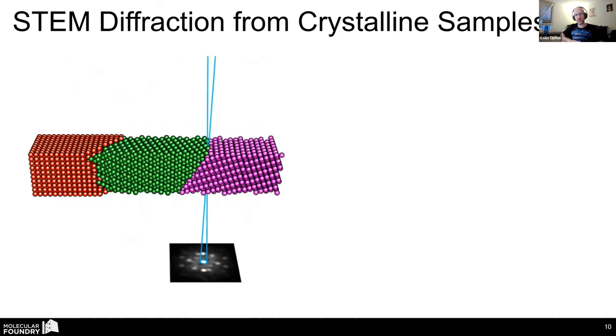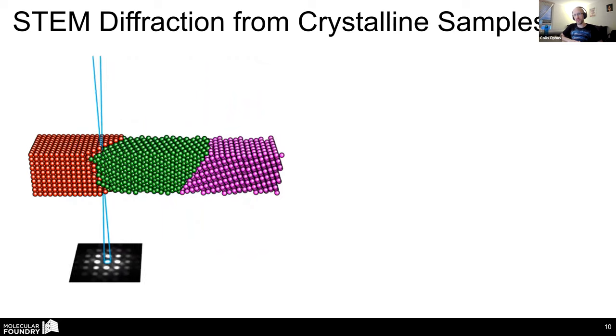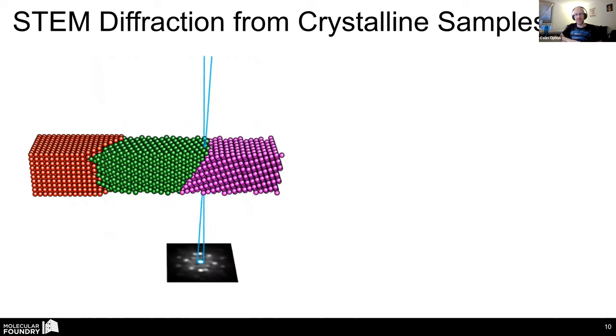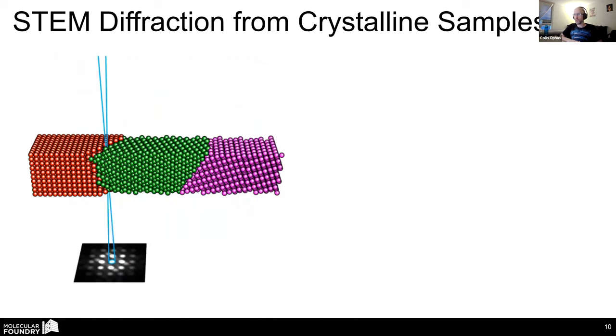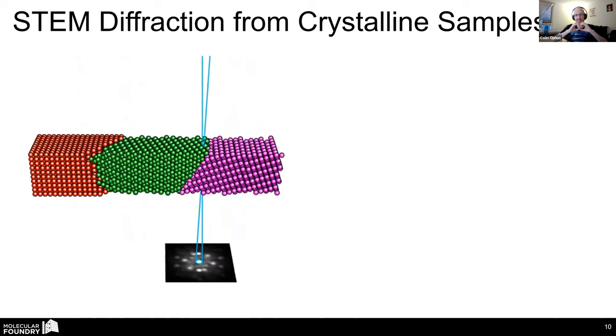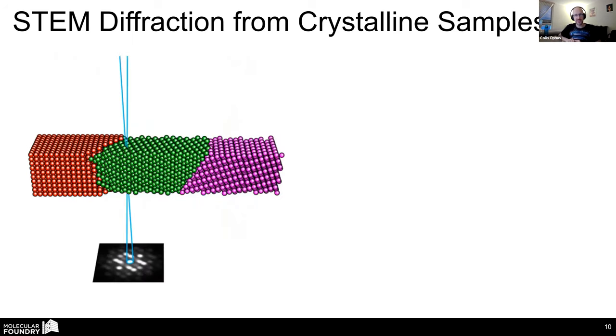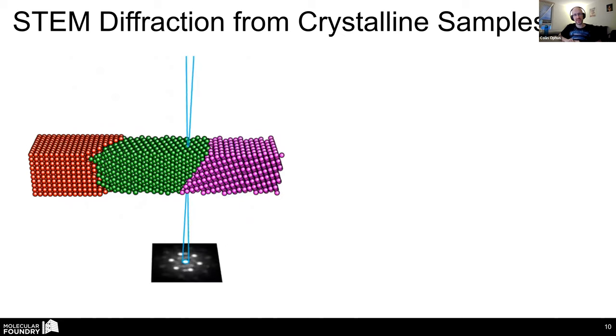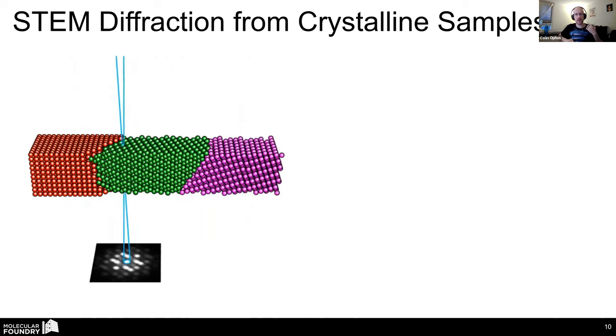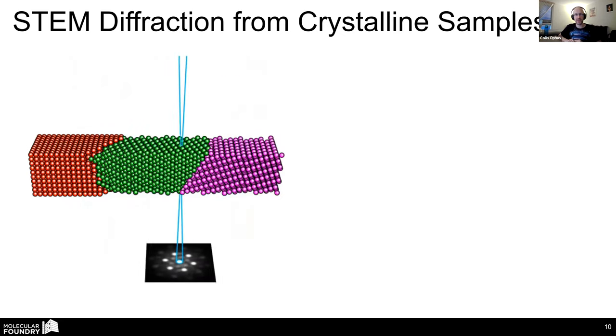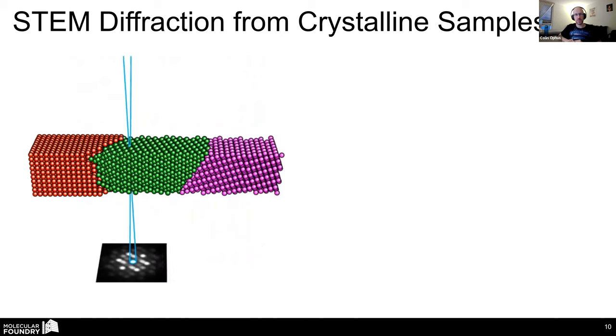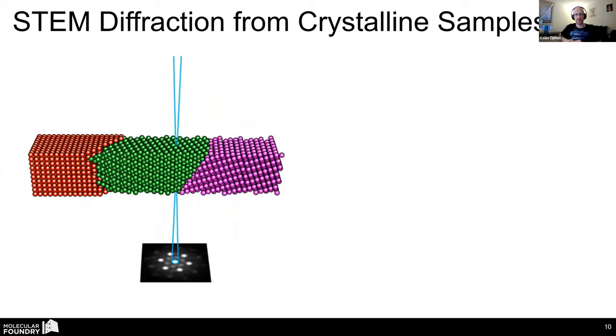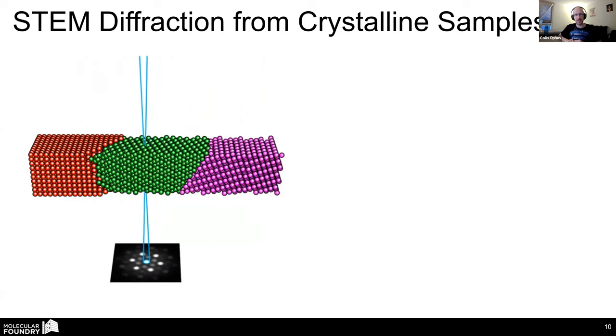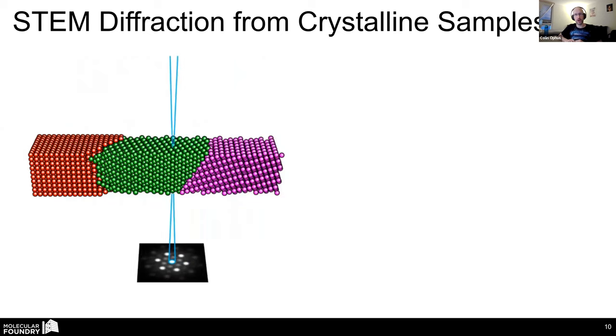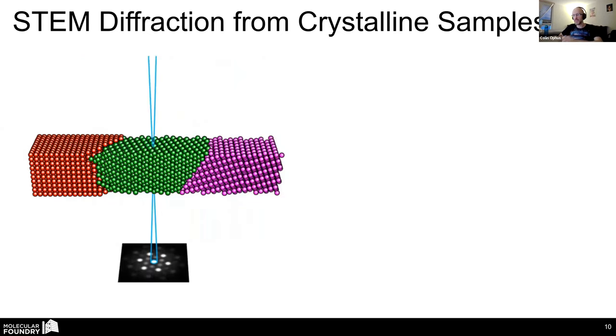But for most of the experiments I showed here, we don't want atomic resolution modulation of the patterns. So we use convergent semi-angles that are very, very close to touching, but not quite touching. And that's usually about 4 or 5 milliradians. That will give you a resolution of about a unit cell, give or take, 1 to 2 unit cells. That's what we use if we really need high resolution in real space. But I would say it's becoming even more popular to use much smaller convergent semi-angles.